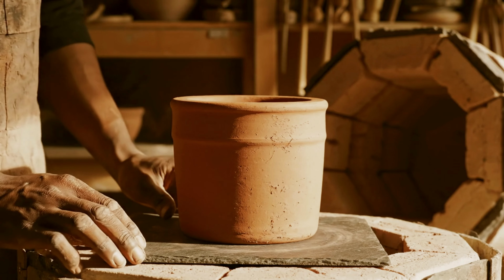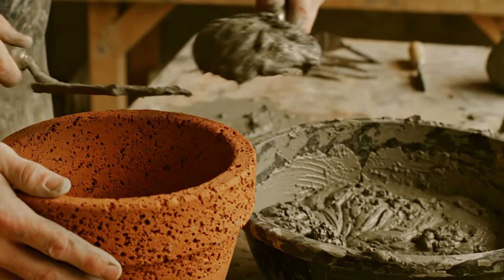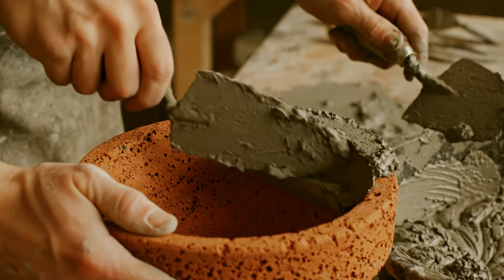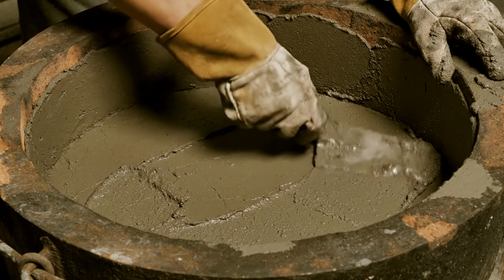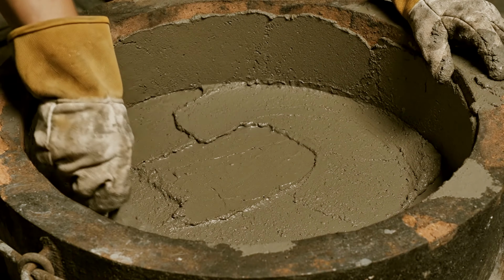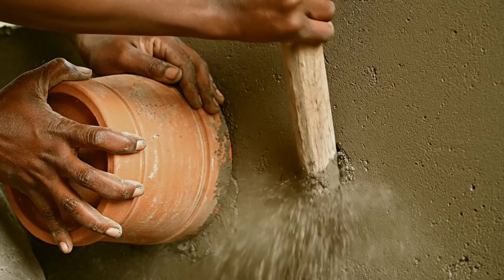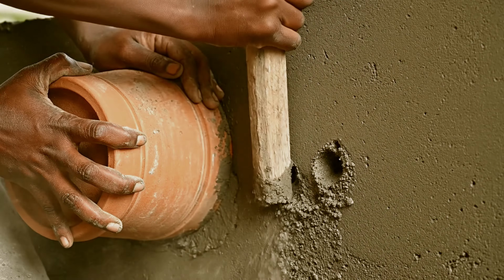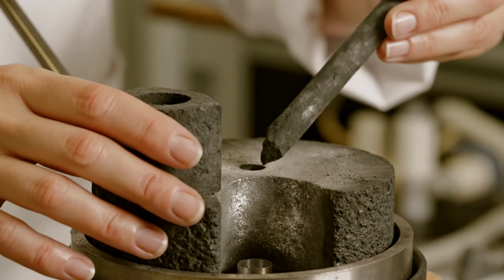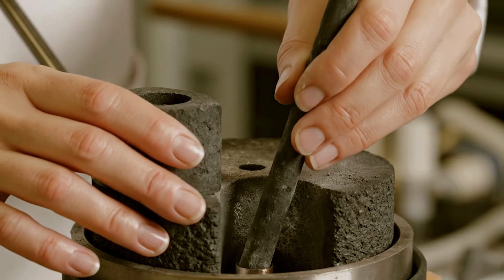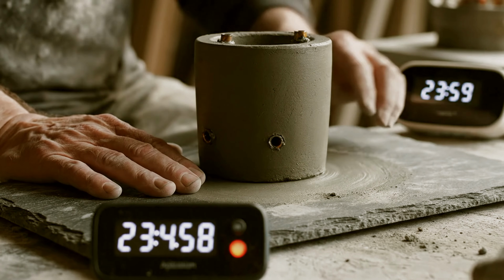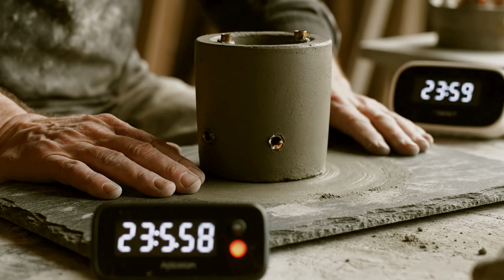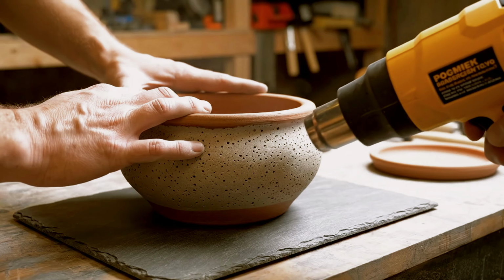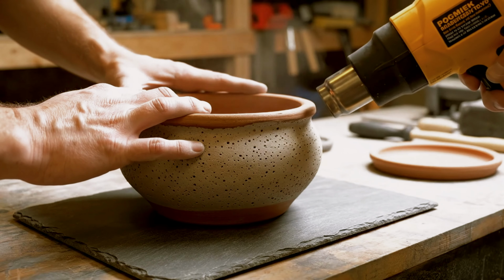Now, the build itself. The chamber is the first thing that has to exist before anything else. A ceramic flower pot, the unglazed terracotta kind, works surprisingly well as the outer shell. It's cheap, it handles heat reasonably well for the outer layer, and it's easy to shape. But the inside of the chamber needs something more capable. Castable refractory cement, the kind sold for lining kilns and wood stoves, gets mixed to a thick consistency, roughly the texture of wet clay, and packed into the inside of the pot to form a smooth, even lining about 2 to 3 centimeters thick. Two small holes get pressed through the wall opposite each other near the bottom of the chamber, just large enough for the electrodes to pass through at a slight angle, angling downward so their tips meet near the center of the floor.